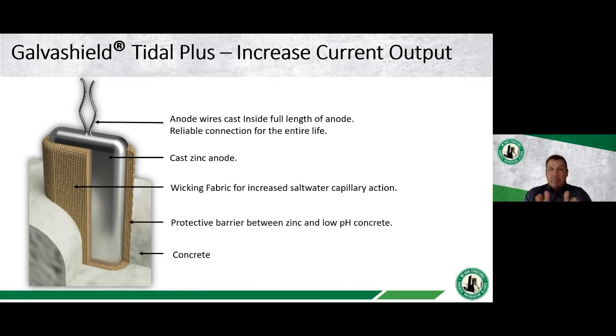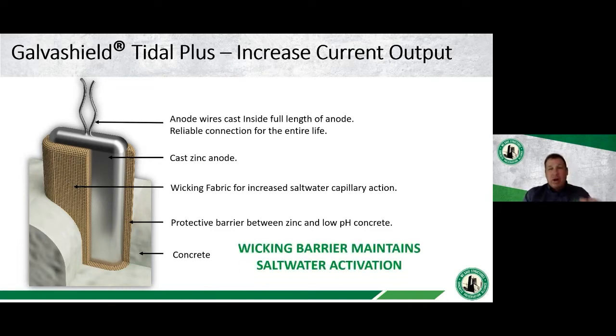So this is going to do two things. This wicking fabric is going to bring salt water up to the higher elevations of this anode so we can increase the activation of the zinc, and thus obviously increase the galvanic current up to the higher elevations of a pile. But it's also providing a protective barrier between the zinc and the concrete. We typically see concrete as being a higher pH environment, but zinc actually starts to passivate when it's embedded in concrete. So if we can keep the zinc away from the concrete with this wicking barrier, we can also prevent our zinc from passivating. So what does all this mean? Basically, it's just a wicking barrier, and it also increases the activation and utilization of this zinc anode.